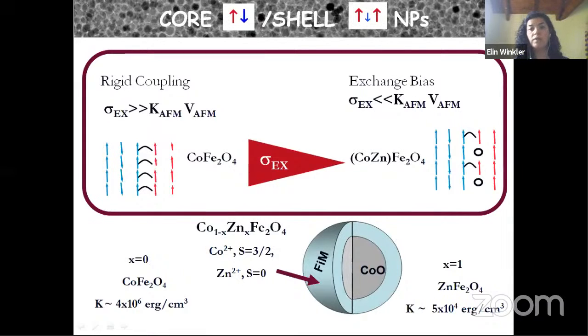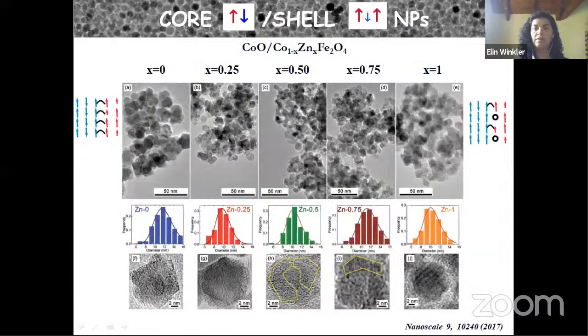Well, we did that. We synthesized all the cobalt oxide core, and we split that in 5 batches, and then we overgrew the shell over the cobalt monoxide, and we changed the shell composition. This one corresponds to the cobalt ferrite. This has 25% of zinc. This has 50% of cobalt and zinc in that place, and so on.